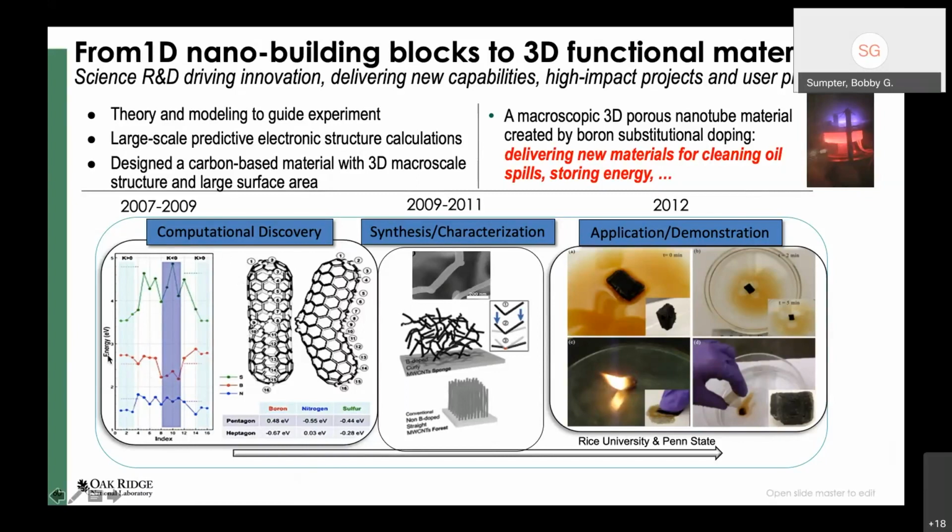This shows the energies of where the atom prefers to sit. And one can see that nitrogen prefers to sit on a positive curvature, while the boron prefers to sit at a negative curvature, energetically more stable. And therefore, as the carbon nanotubes start to grow, if there's a nitrogen in there, they'll grow and close that growth off, and you'll get shorter tubes. But if there's a boron in there, it'll change the direction of the growth, and you get this elbow.